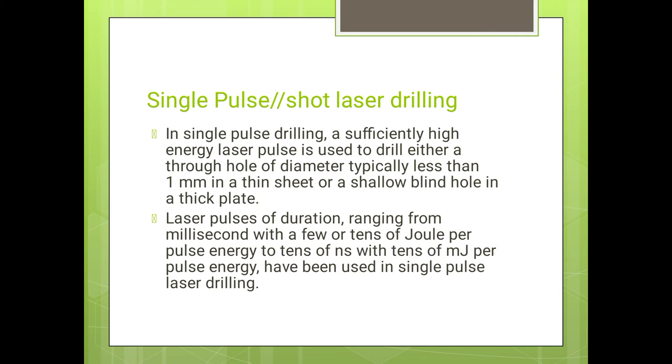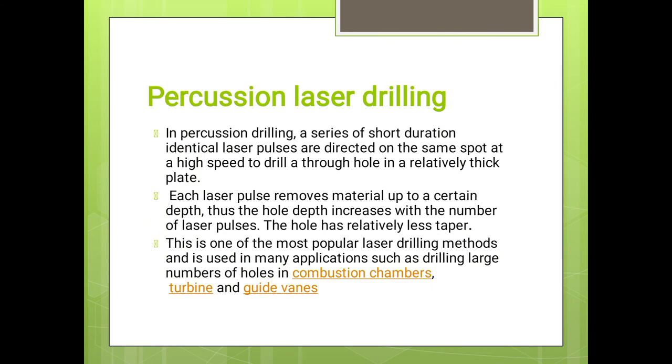In single pulse laser drilling, the duration of the pulse may be from milliseconds, with pulse energy from millijoules to a few tens of joules. Percussion laser drilling: a series of short duration identical laser pulses are directed at the same spot at high speed to drill a through hole in a relatively thick plate. This is the most popular laser drilling method and is used in many applications such as drilling a large number of holes in combustion engine chambers, turbines and guide vanes.